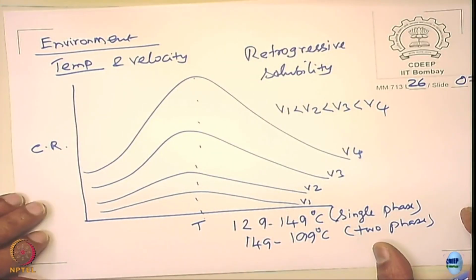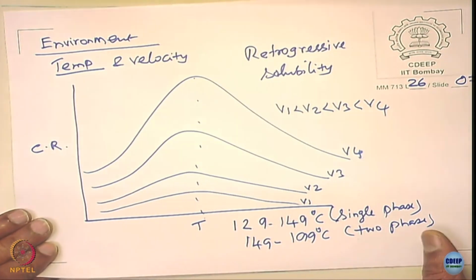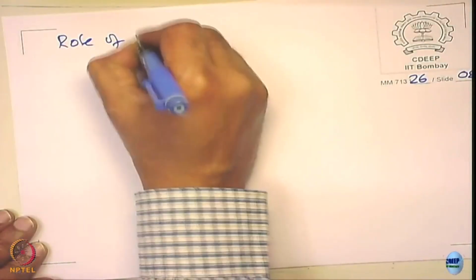If the pH is not properly maintained, I do not think that chromium will be sufficient to form any film at all. So from that point of view, the 1% chromium is good. Of course, if you increase the chromium content it is even better, but the cost increases. In industry, every penny is important. You do not want to keep increasing the MOC with better materials, because that is going to cost more. Now, what else can improve the film formation, interestingly, is the role of dissolved oxygen.